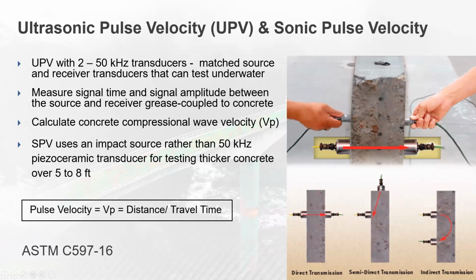You can test indirectly, say on a column or beam from a side to another side or on the surface, but here you only see an inch or two in, and we probably use surface waves most of the time instead of pulse velocity. This is a weaker test than doing that.